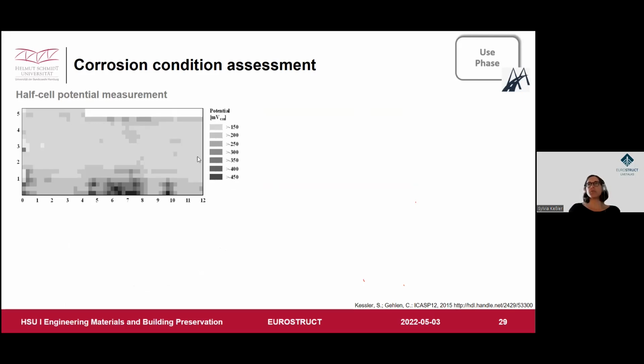You see here the potential, and normally, at least according to the German specification, we look at the spots with the most negative potential in combination with a pronounced gradient of the potential. So here I would guess I have a certain corrosion probability as well. But what does it really mean? How can I quantify this data?